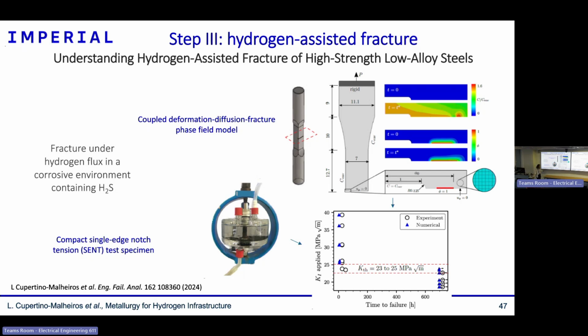For those samples we have done, usually you do some finite element simulations with Fick's law, then you know the time, and then you just leave that time. So that is what was done for the samples. For BCC, it diffuses relatively fast. If you have lab samples, in a few days it's fine, it would diffuse completely. So you can do the simulations just to verify.